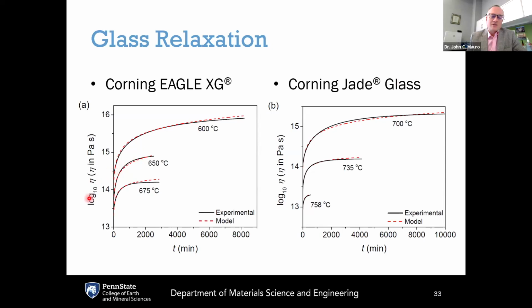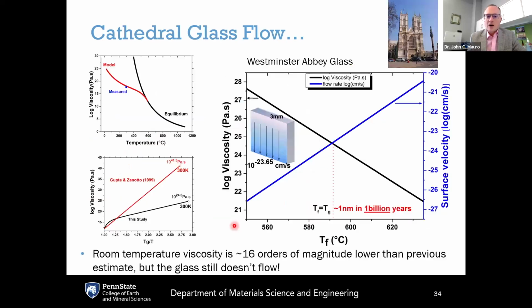What you can see here is that the viscosity of either Eagle XG on the left or Jade on the right initially has a lower value, but then over time, if you hold the glass isothermally, either at 600, 650, or 675 degrees C, or at these higher temperatures for the glass on the right, the glass is relaxing. Over time, the atoms are slowly moving. They're slowly approaching the liquid state. And as they do that, all the properties of the system change, including its viscosity. And here you can see that over time, the viscosity is increasing by 1 to 2 orders of magnitude. So it is undergoing enormous changes. And this requires very precise measurements experimentally, as well as some fairly sophisticated theories to make the model predictions.